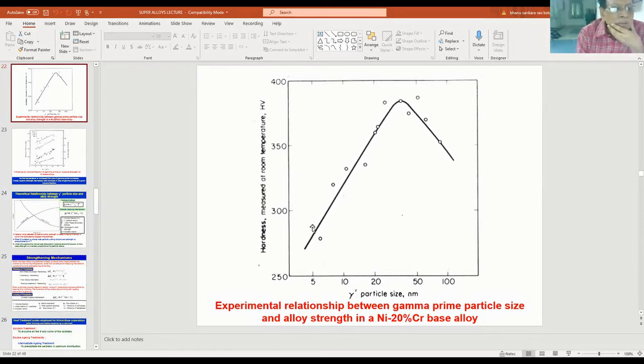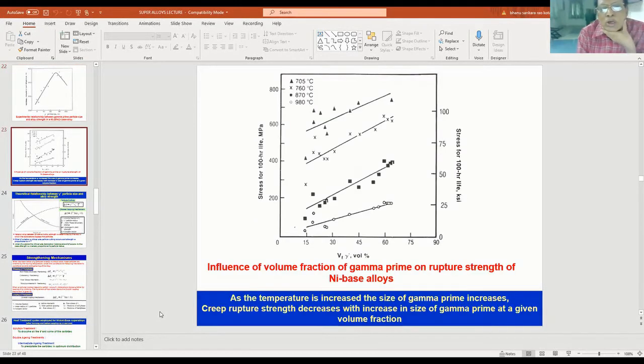Look at this graph, the creep life, how it is varying as a function of volume percentage of gamma prime at different temperatures. At 705 degrees centigrade, on increasing the volume fraction of gamma prime, your strength is increasing. That is creep strength. You see, rupture life is much more at 705 degrees centigrade, and it keeps on increasing. On going to 760 degrees centigrade, still volume fraction increase contributes to creep rupture strength, but it's much less.